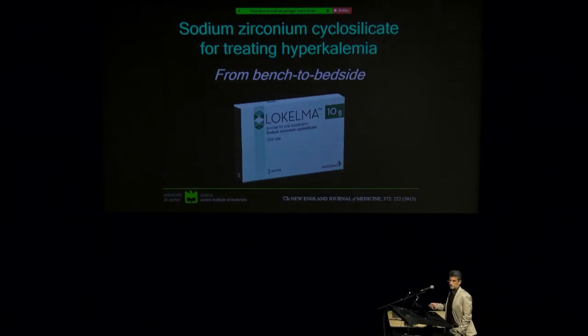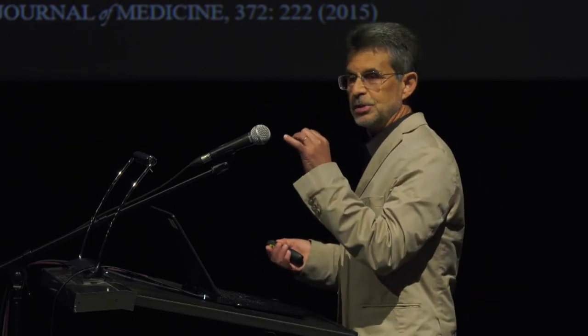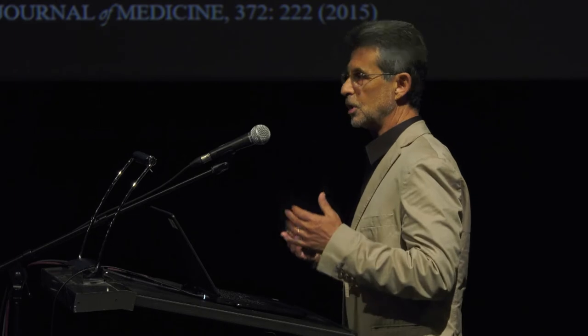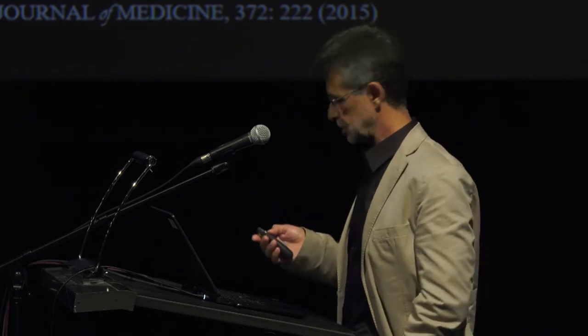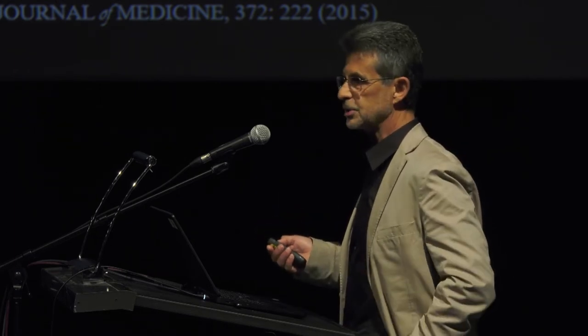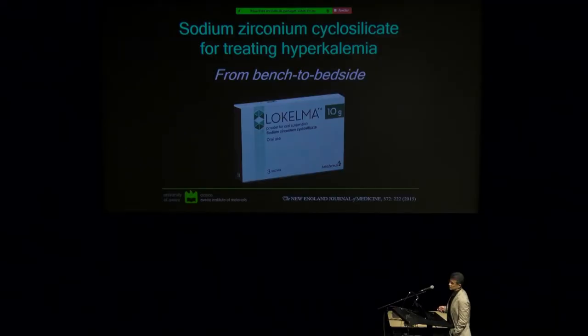But this was perhaps totally unexpected, because one of the worst materials we made, worst because it is an extremely small porous material, we almost didn't bother to publish it because it was useless for catalysis or something. But it turned out many years later that it has medical applications. It's a sodium zirconium cyclosilicate, which is now used, it's on the market, to treat excess potassium in blood, hyperkalemia.